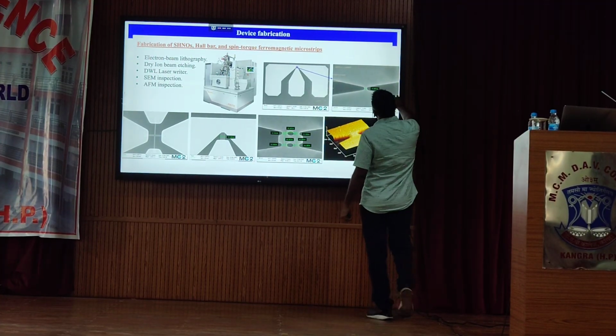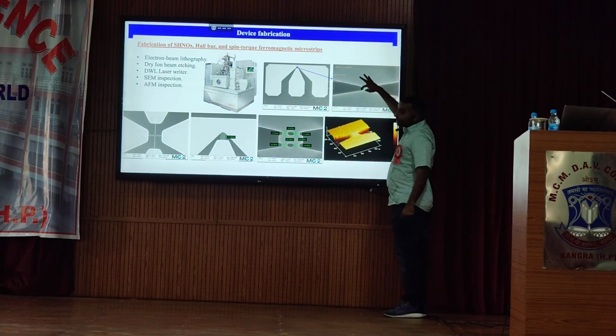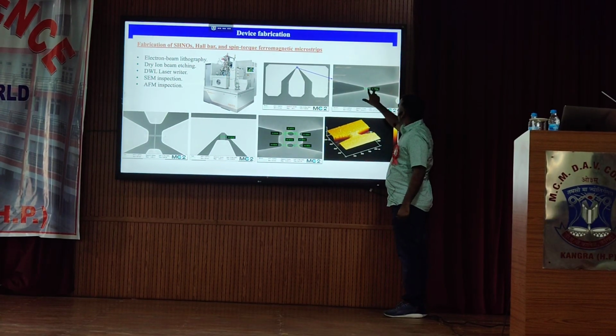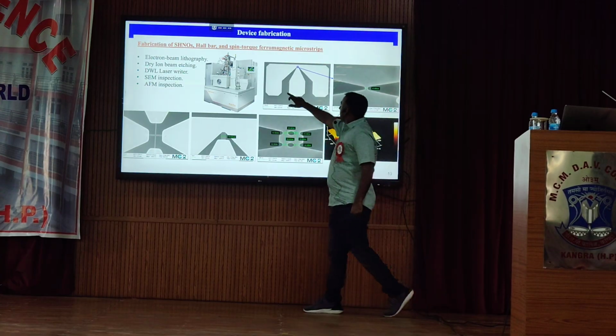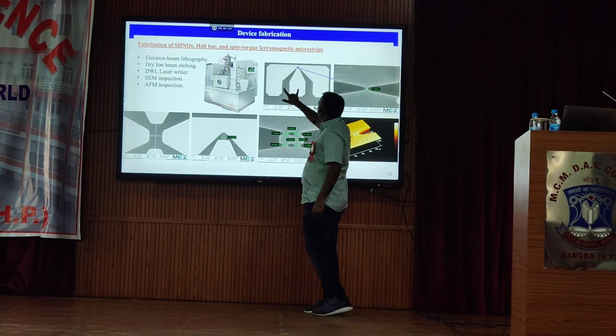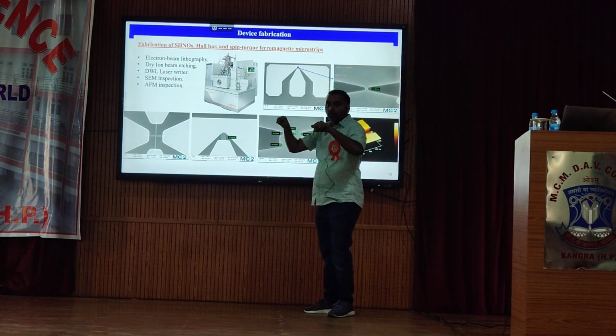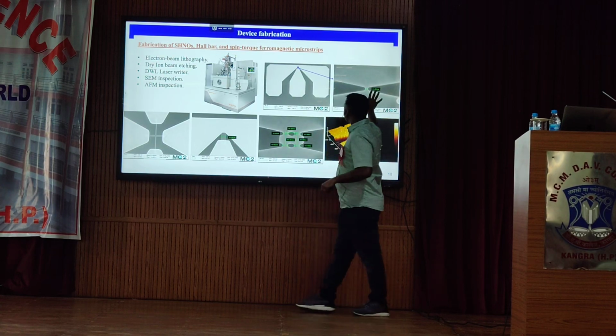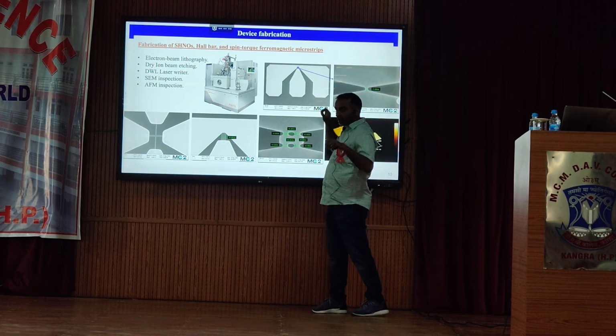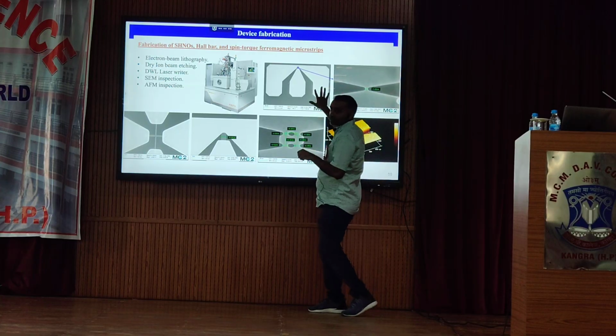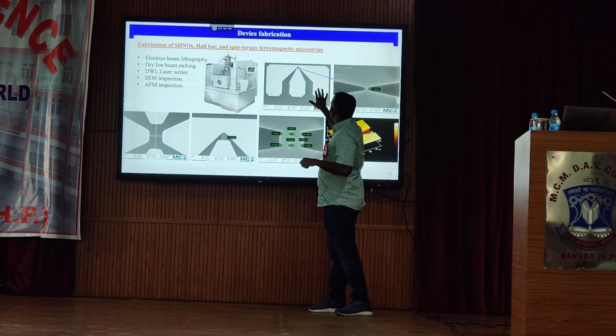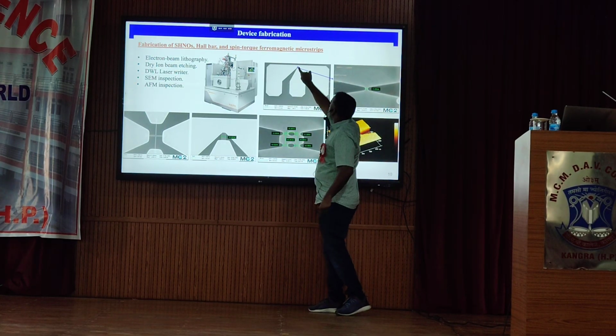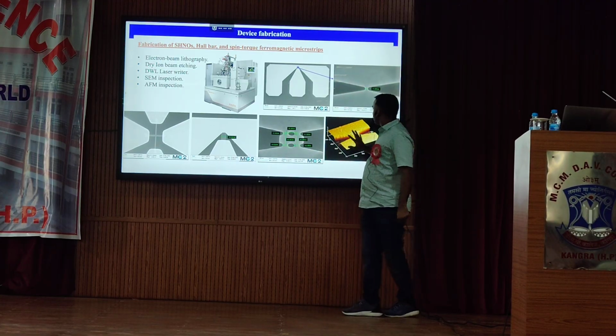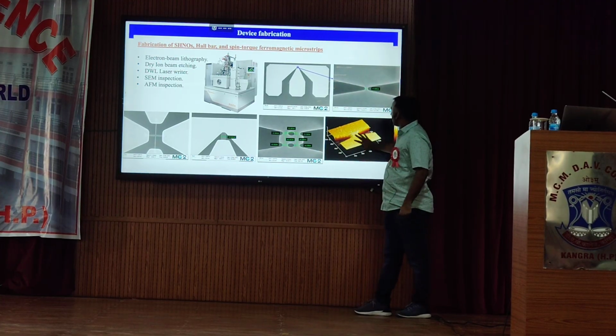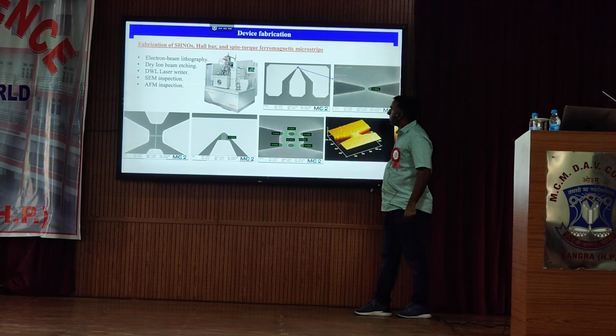Here you can see nice constructions made on the 50 nanometer scale. This construction is 50 nanometer, and these lines are contact pads. These pads we use to measure the sample. These are slightly bigger than the devices, so we cannot make contact to the devices if the contacts are so small. So these are used for the contact, and the devices are here. The scale of the device is here. This is the atomic force microscopy image of this device.